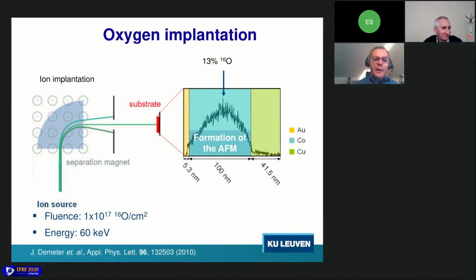Okay, in the ion implantation process, what actually happens is that you have a separation magnet that picks out just one isotope. In this case, it's oxygen 16, and you bring that beam into the sample. So if we blow up what's happening into the sample, you see here you have the substrate, here you have this thin gold layer, and this is a simulation of the distribution of oxygen ions into the film.